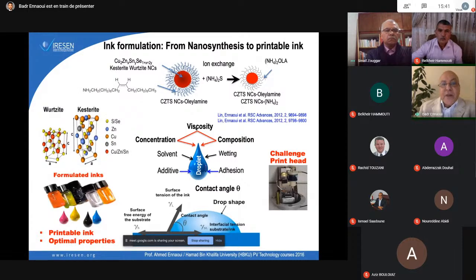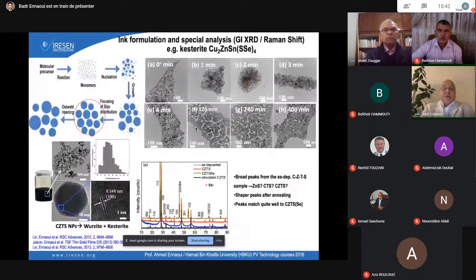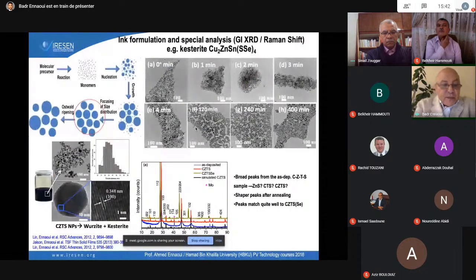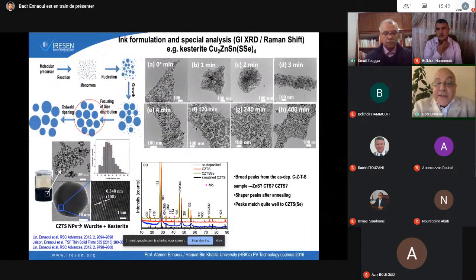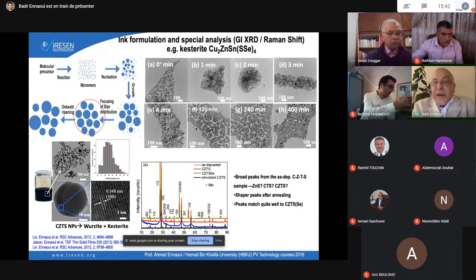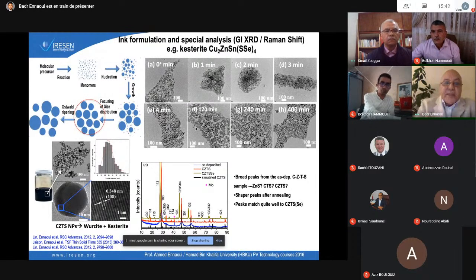I have here some work that we have done, and the references are on the screen. We prepared the nanoparticles at different times. We make an injection, and we take the particles at different times, 1 minute, 2 minutes, 3 minutes, in order to see the dynamics of size growth.